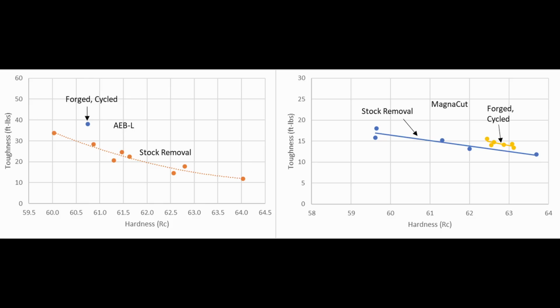And I have a video all on this topic. Here I have results for AEB-L and MagnaCut, where we came up with an optimized annealing procedure for the steel to make it a little bit finer. We found that we could give a small improvement in the toughness for a given hardness by optimizing that annealing procedure. So even with stainless steels, there is some possibility of improving properties.